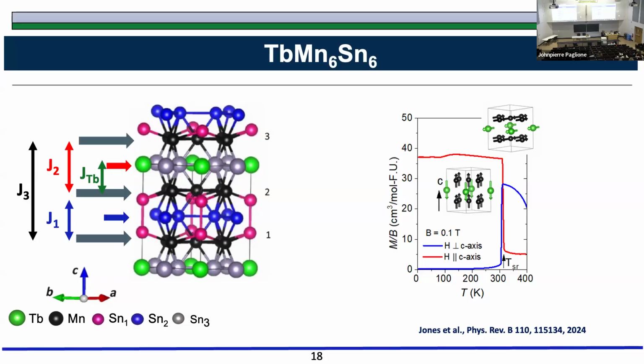As you lower the temperature, these ferromagnets lying in the plane want to go out of plane. They were like this, right? And then when they move out of plane, they do so simultaneously like this. And you can see that by measuring susceptibility, right? In one direction, susceptibility was small here, and then it goes up, right? So the spins are pointing along this direction, which is the c-axis. And here, originally, the susceptibility was large because the moments were in the plane. And then when these spins go out of plane, the susceptibility drops.